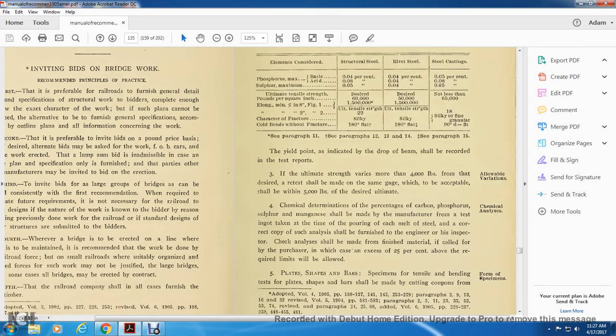The chemical determination of the percentages of carbon, phosphorus, sulfur and manganese shall be made by the manufacturer from a test taken at the time of pouring of each melt of steel, and a correct copy of such analysis shall be furnished to the engineer and the chief inspector. Check analysis shall be made on the furnished material when called for by the purchaser, in which an excess of 25% above the required limits is allowed.